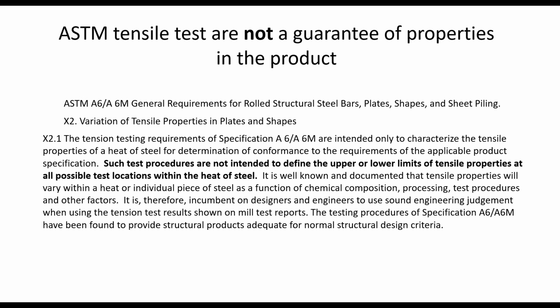And in that standard, to clarify this, there is an Appendix X2, and you can see in bold here that the test procedures for tensile testing are not intended to define the upper and lower limits of tensile properties at all possible test locations within the heat of steel. The first sentence says it's to determine the characteristics of the heat of steel for the requirements of the specification, not to provide tensile test results that you can use guaranteed in every place in the product.